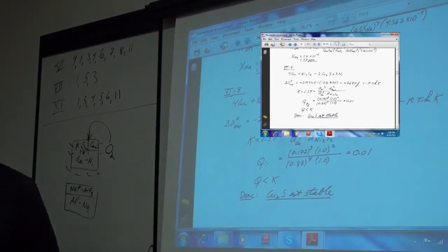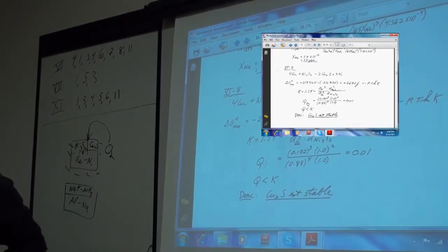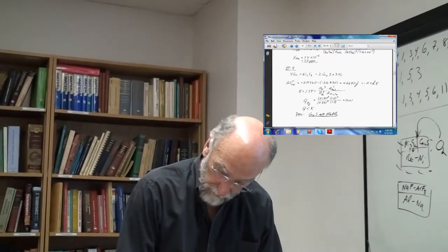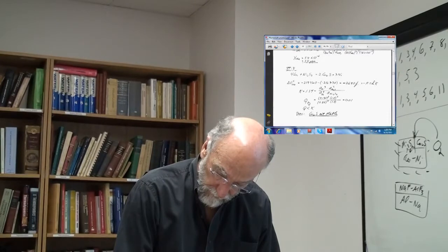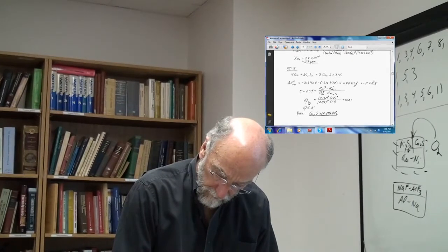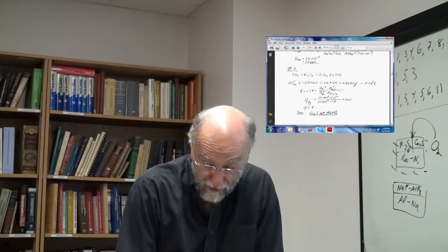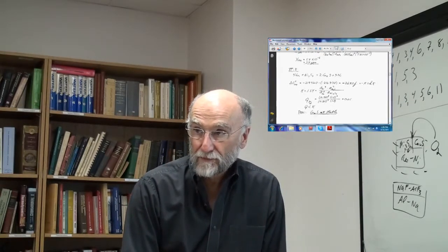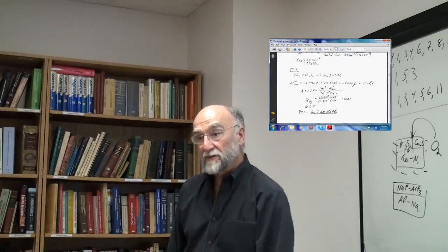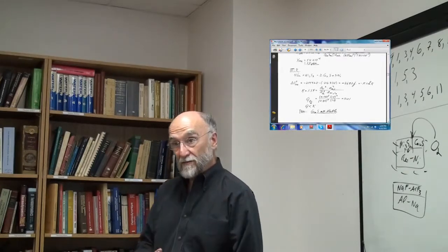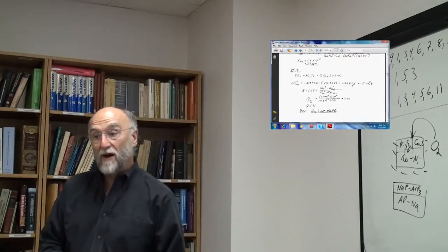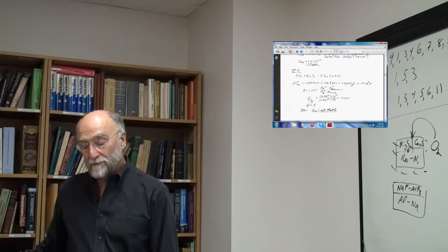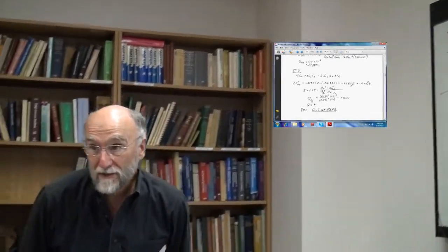Yeah, but what about question 3? Because in question 3, the delta G of reaction is equal to delta G naught. Well, yeah, but that's only because the oxygen pressure is 1 atmosphere. In question 3, delta G is delta G naught because you have pure copper, the pure copper oxides, and the oxygen is at 1 atmosphere, which is the standard state oxygen pressure.